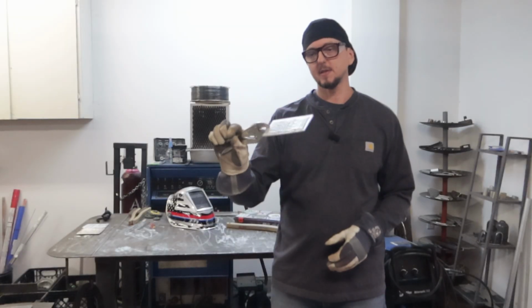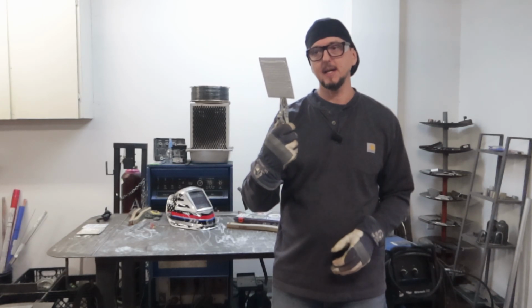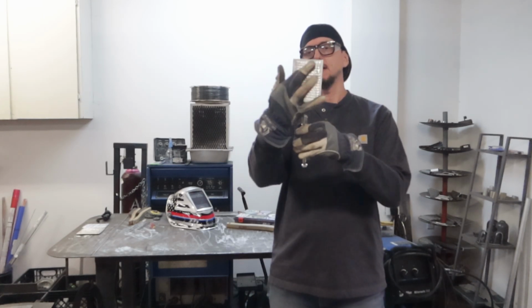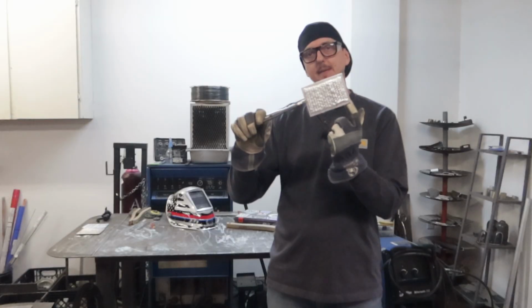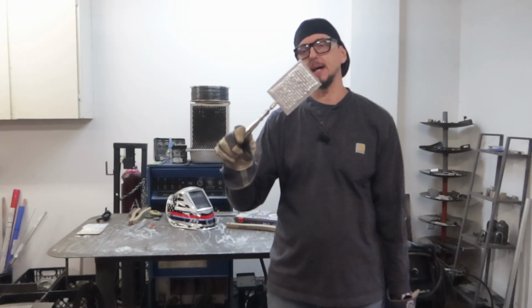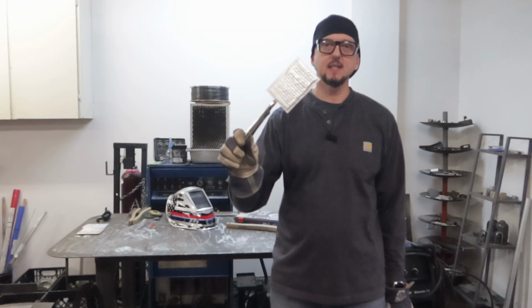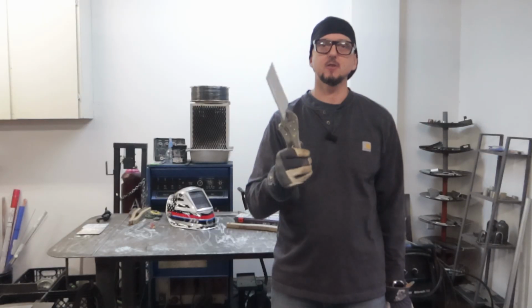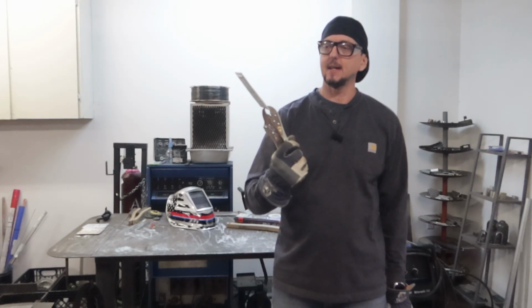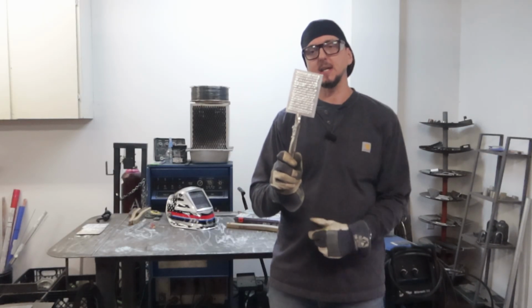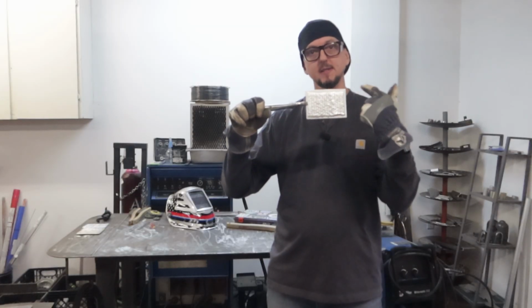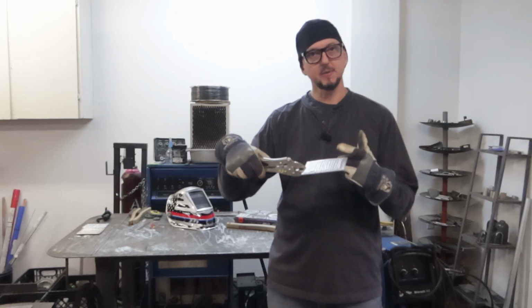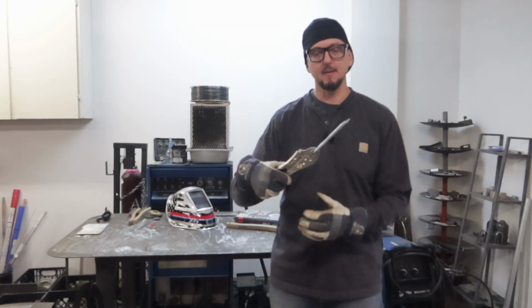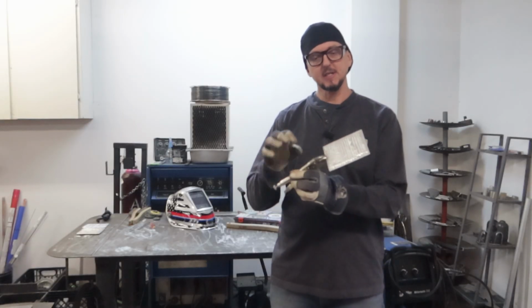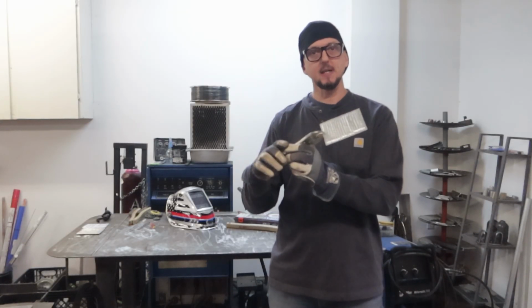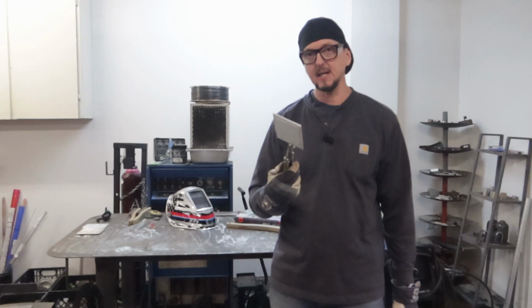So there you go. We've surfaced both sides of this plate, all the way on both sides, overlapping each bead by about 1/16 of an inch to 1/8 of an inch, something like that. And if we surface both sides, then we can even switch directions and put a new layer on both sides, and just keep doing that, managing the heat. And over time, you'll get a thicker piece that will be able to take more and more heat.